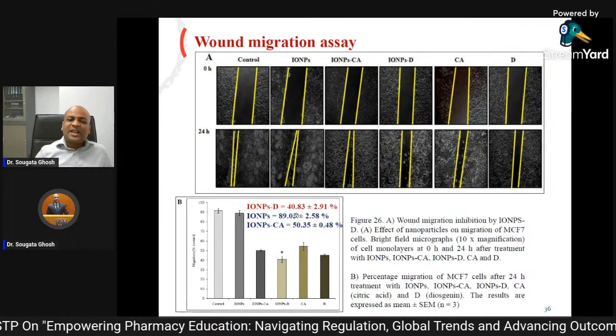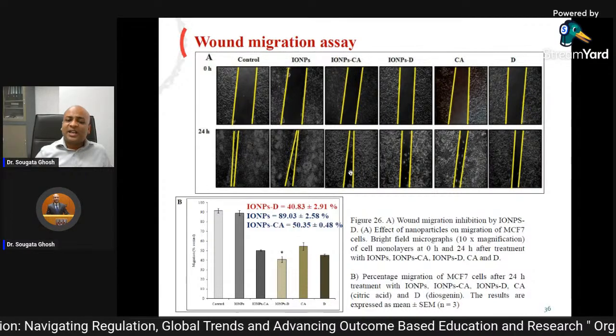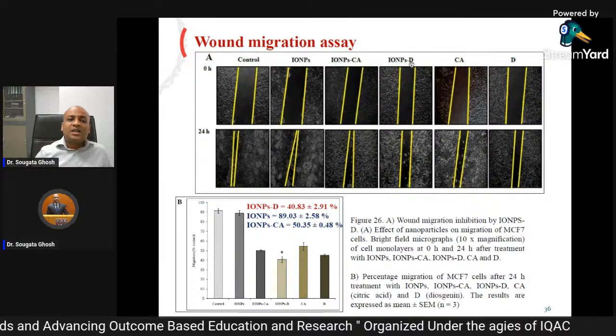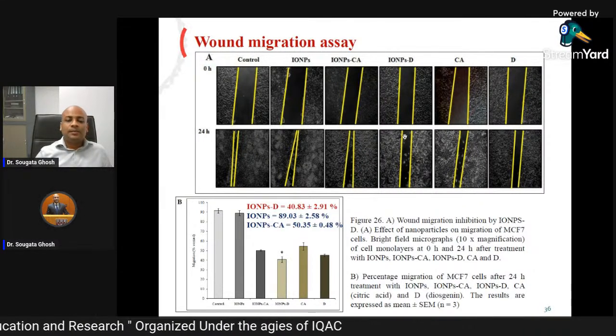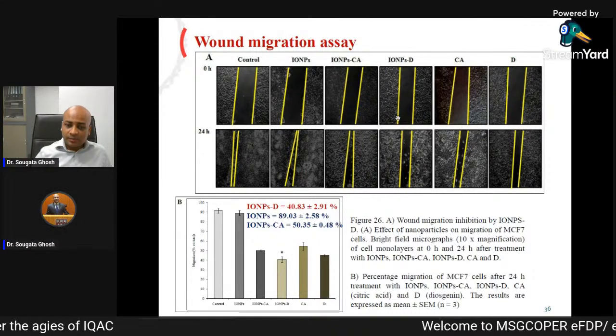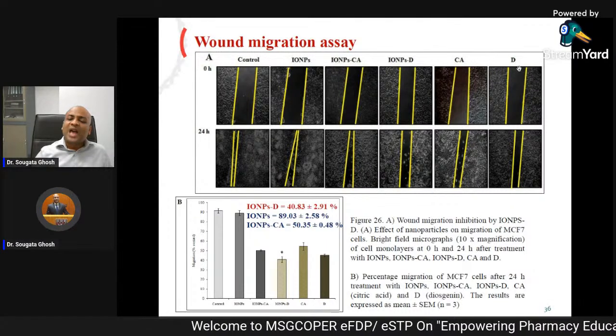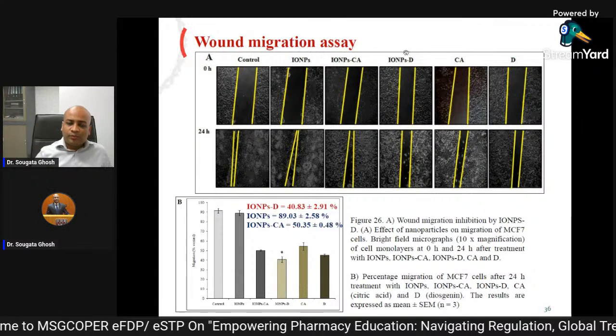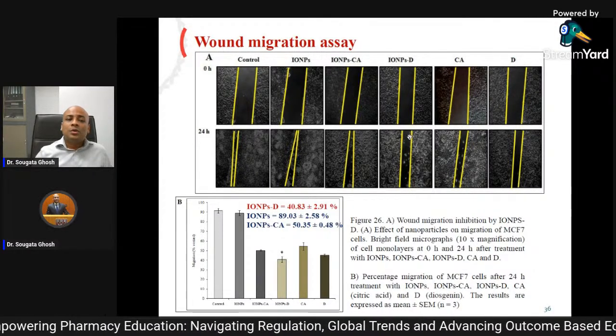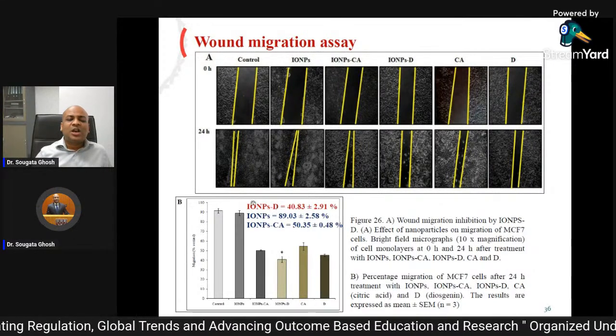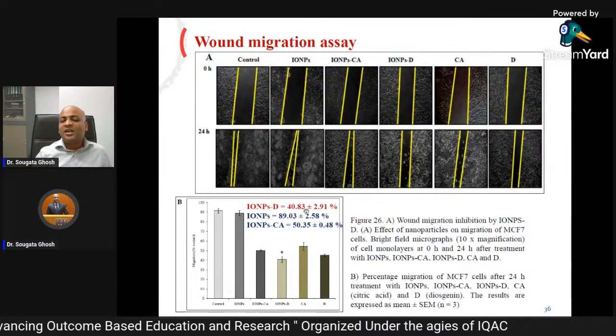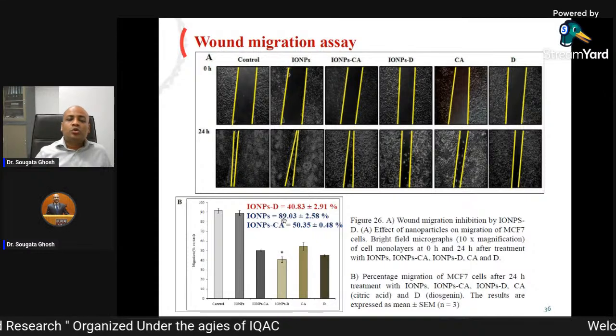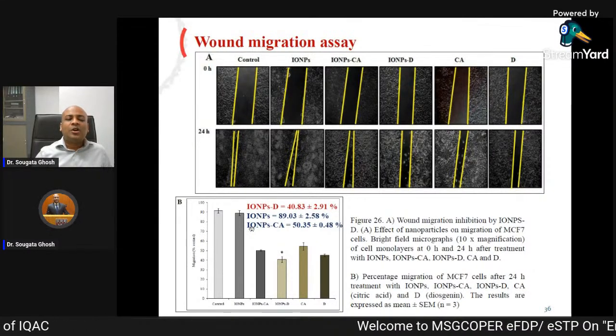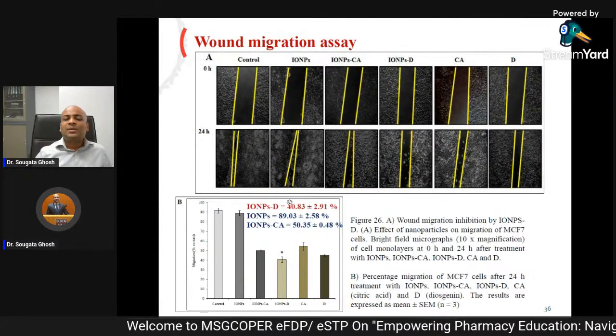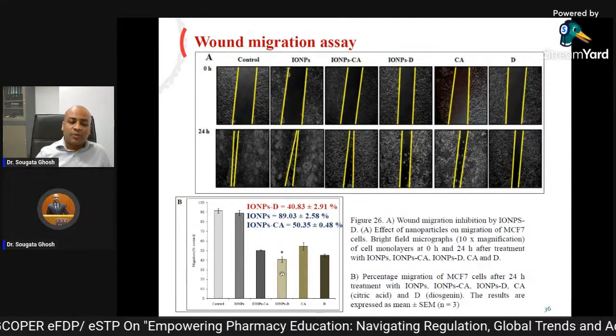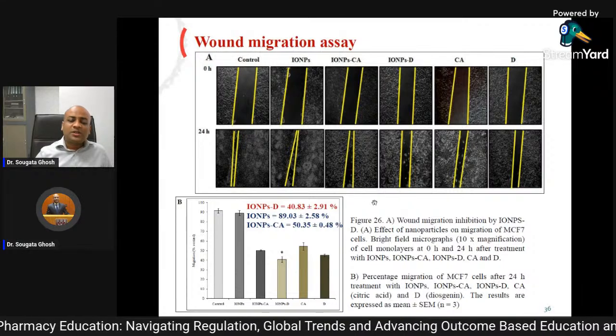Here with iron oxide nanoparticle, the gap was almost sealed. With iron oxide citric acid, the gap was less sealed as compared to this. But with iron oxide diosgenin, the gap was not sealed. That means the migration of the cells was inhibited by this. Similarly, with only citric acid, there was less migration. With diosgenin also, there was less migration. So iron oxide functionalized with diosgenin was showing more inhibition of wound migration. You can see diosgenin functionalized iron oxide nanoparticle only showed 40% migration. Iron oxide nanoparticles showed around 89% migration. And iron oxide nanoparticle citric acid showed 50% migration. So the lowest migration was in diosgenin functionalized iron oxide nanoparticle. So it was very efficient.